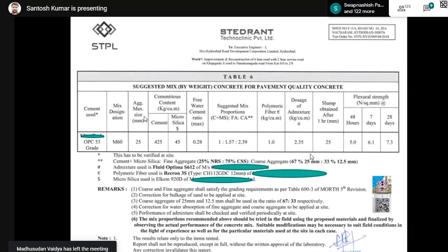Water cement ratio was 0.28. The proportion of concrete was 1:1.57:2.39. And this concrete was designed for flexure strength. The authority, Hyderabad Road Development Corporation, required the concrete to attain the flexural strength of 5 Newton per mm square at the end of 48 hours.